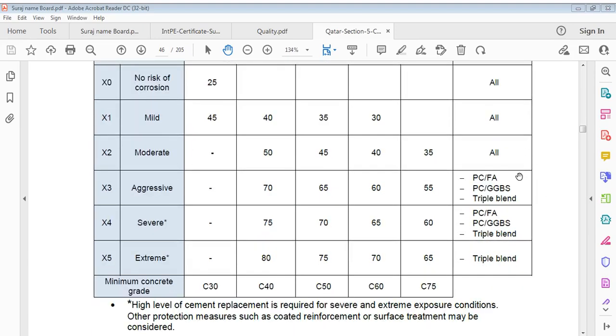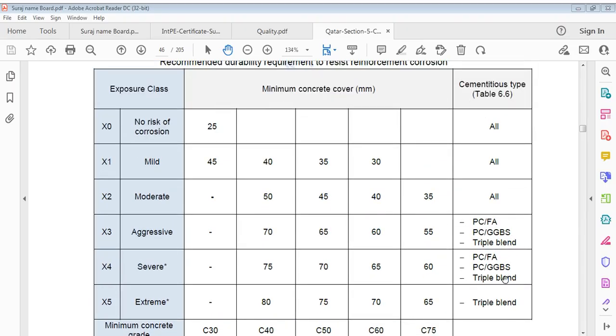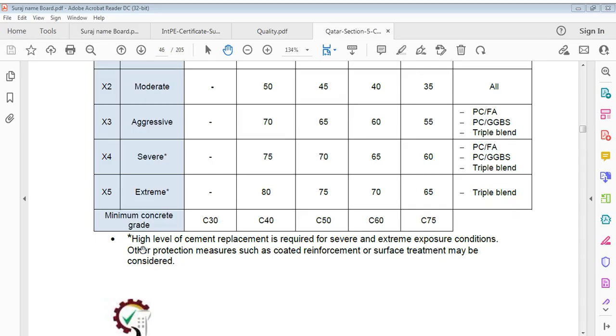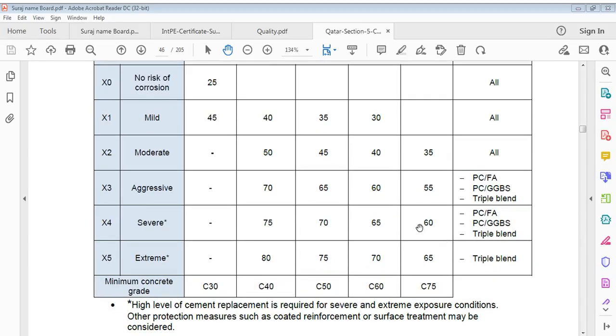And what combination of cement is given here, we have already discussed this. A high level of cement replacement is required for severe and extreme exposure conditions. Other protection measures such as epoxy coated reinforcement or surface treatment may be considered. This gives some idea what cover thickness can be taken for good durability, and how much OPC can be replaced by GGBS. Sometimes we have used up to 70% replacement of OPC